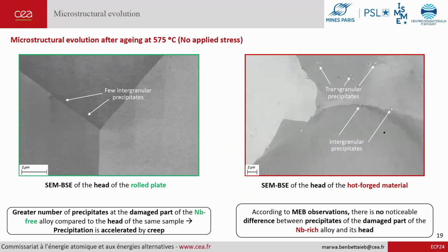If we compare now our results for the damaged part to the heads of the specimens, which are non-strained parts, but hot-aged ones, we can see here a low number of intergranular precipitates for the niobium-free material, which is lower than what we have seen for the damaged part. And then we can say that the creep accelerates the precipitation in this case. In the other case, for the niobium-rich alloy, we can't really notice any differences between the head and the damaged parts.